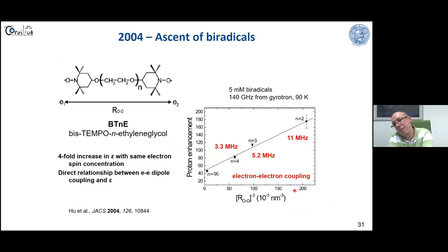This put us on the idea of reinventing what Kan-Nian Hu did in 2004, where they coupled two nitroxides together by a polyethylene glycol linker. With this, they were able to introduce electron-spin couplings without having to increase the concentration of the polarizing agent, since you have an intramolecular coupling. They could nicely show that the DNP enhancement increased with the coupling between the two electrons through shorter linkers.